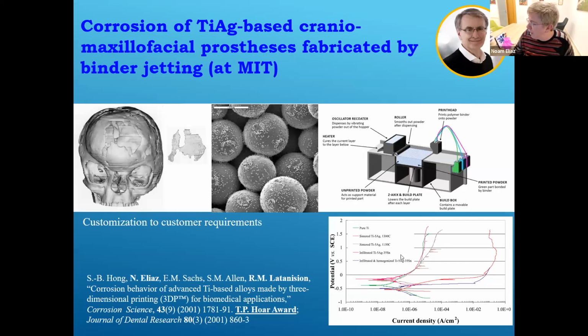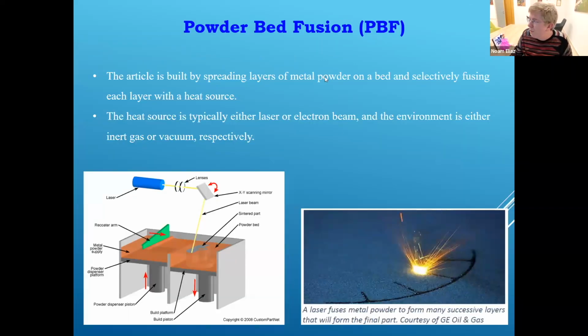On the right bottom side, you can see some of our corrosion studies. I won't get into the details, but basically the corrosion behavior depends on the porosity of the printed part, and with the titanium silver, we could get corrosion behavior that was as good or slightly better than commercially pure titanium medical grade. And we can talk about the effect of silver on the hydrogen evolution reaction and so on, but I will not get into it now.